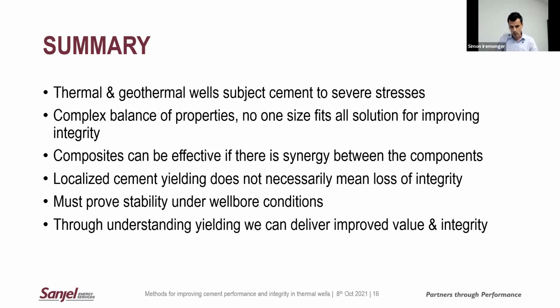One thing that's important to look at, if you go for very, very long fibers, your slurry properties can start to look very bad. You get very high viscosities and bad mixability, and it's hard to disperse them. So typically we focused on shorter fibers, typically less than 5 millimeters, to make sure that we could get good slurry properties and still get good tensile strength enhancement.